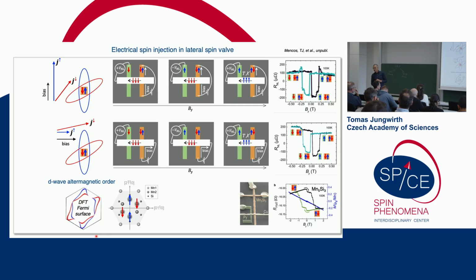There is. Yeah, there is. There is a first transition from paramagnetic to this collinear phase. And then there is a second transition, which depends on whether it's a thin film or bulk. And we can have a long discussion about the difference between thin films and bulk, because it's crucial. In bulk, there is no altermagnetic order, because you have a doubling of the unit cell in the bulk. And they don't see an anomalous Hall effect, etc., etc.